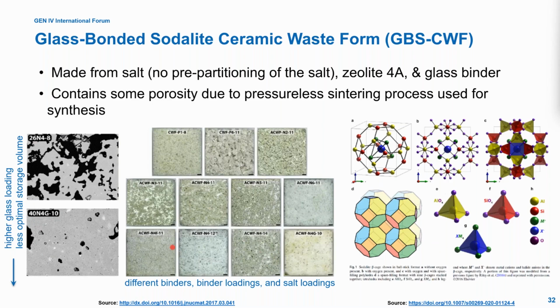These are some examples of different glass bonded sodalites that Steve Frank made at Idaho National Lab. The different colors represent different binders, different binder loadings. Binder means glass here, and different salt loadings. I talked about porosity as a problem. This is a 26 weight% glass bonded sodalite with 8 weight% salt. In this, you can see the black represents the porosity. The porosity is rather high in this material. Whereas if I go to a 40 weight% glass and a 10 weight% salt, I can reduce a lot of that porosity, but now that I'm adding more glass, I'm making the waste form larger. So I'm negatively affecting my storage volume, but I am positively affecting my porosity, and my durability should go up here.